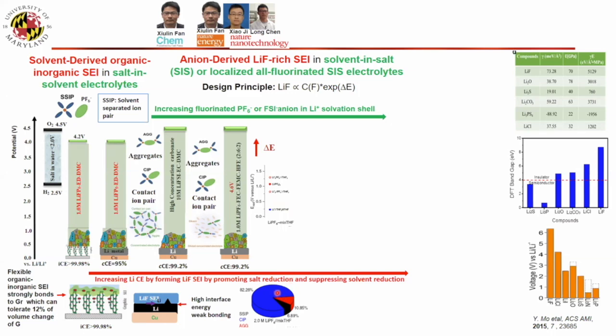Second, in the PF6 mixed with THF, we also have a lot of CIP and a lot of AGG, but the SSIP is very small. So not only is the concentration of anion high, the reduction potential gap also increases. In that case, using these electrolytes, we can reach a high coulombic efficiency of 99.8.